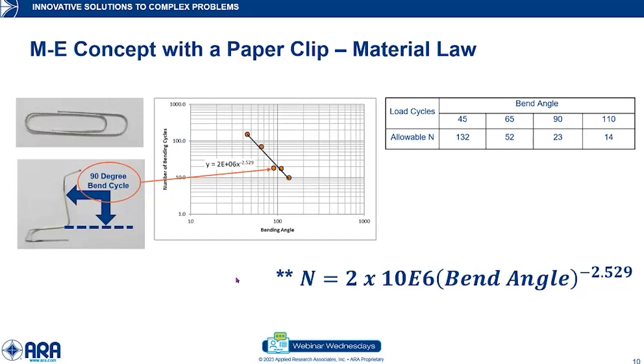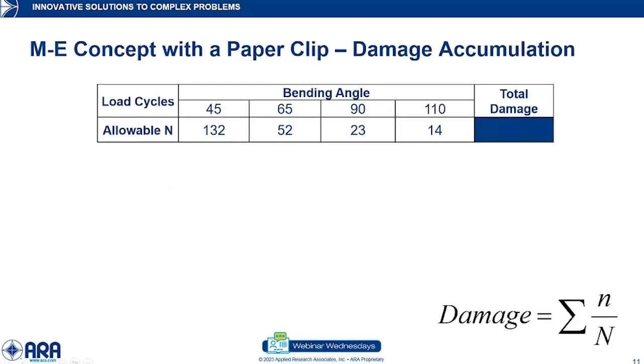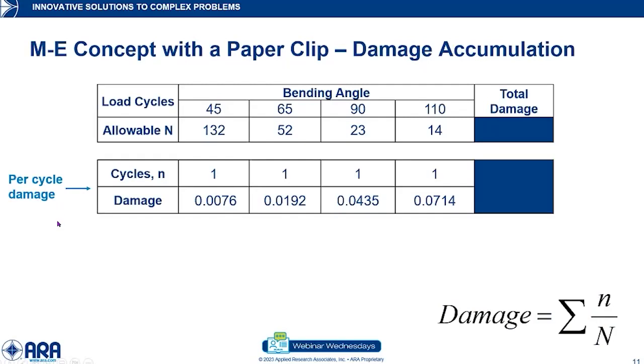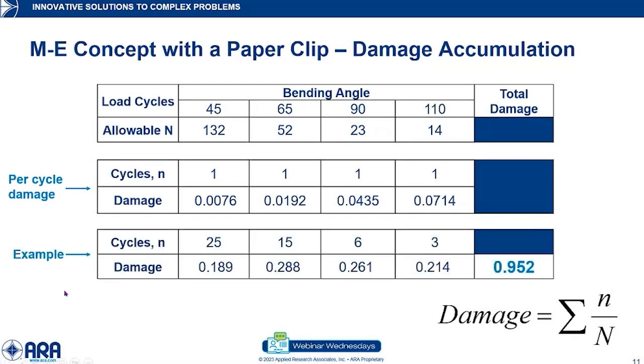52, and so on. And if we plot this data, you can see on a log-log scale, we can come up with a formula relating the bending angle to the number of possible cycles. Taking this a step further, we can figure out what the damage per cycle is. So from that table, if we were to bend it one time at 45 degrees, the math is dividing 1 by 132, which is the number of total cycles you can do at 45 degrees, and your damage accumulation is 0.0076. So then you can also accumulate damage bending it at different angles for a different number of times.